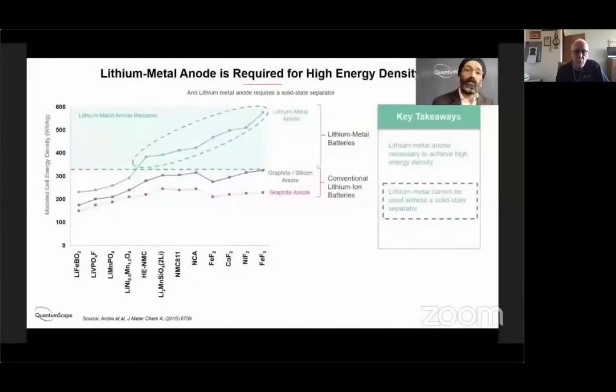So a quick summary of the different options available to someone trying to improve battery performance. This slide looks at a dozen different next generation cathode materials and 3 different anode materials. The cathode materials are on the x-axis and the anode materials are shown on these 3 lines or curves on the slide. And the main takeaway from this slide is that it doesn't really matter which next generation cathode material you use. If you don't use lithium metal as the anode, then you can't get much above 300 or the low 300s in terms of watt hours per kilogram. So the key requirement is lithium metal anode.